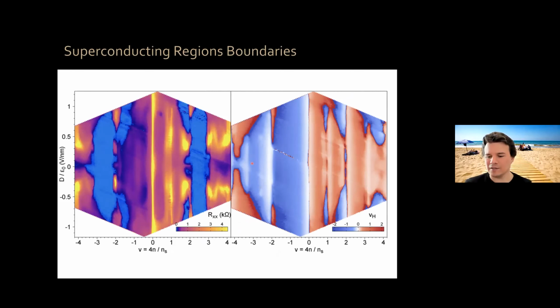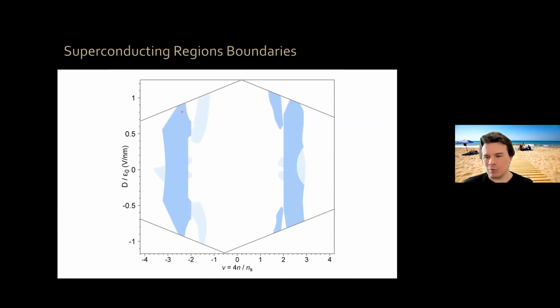So now we have these two phase diagrams, in terms of Hall density and in terms of resistivity, and we can see what features here correspond to what features on the other. Because superimposing them directly color-wise would be very messy, let me do the following. I want to pay special attention to the superconducting boundaries. This is the phase diagram as a function of displacement field and filling factor. These blue regions are regions where superconductivity exists. In the darker blue regions, superconductivity is very strong. In the lighter blue regions, it's weak superconductivity, but still there.